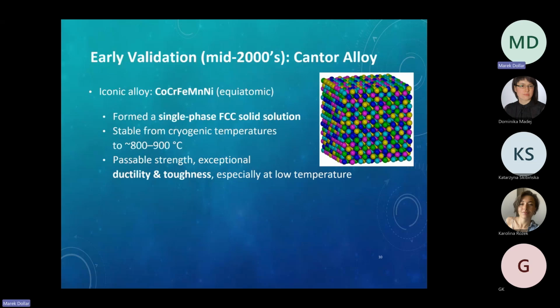Atoms are distributed randomly, but because there is some pattern, if you will, because it's 20% of each. And very quickly, first mechanical studies prove that this Cantor alloy has a stable microstructure from temperature as low as liquid nitrogen temperature to 800, 900 degrees C. That was very interesting. Because there is no brittle to ductile transition, really, they were looked at as very promising cryogenic alloys, not as much high temperature alloys.